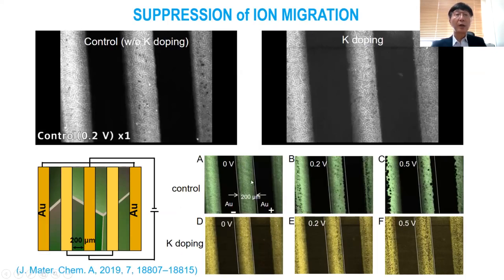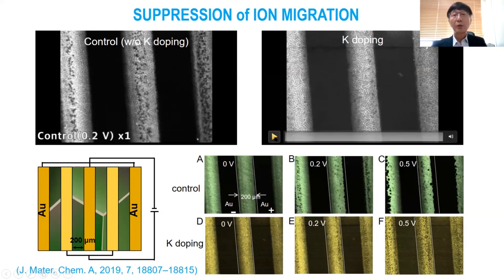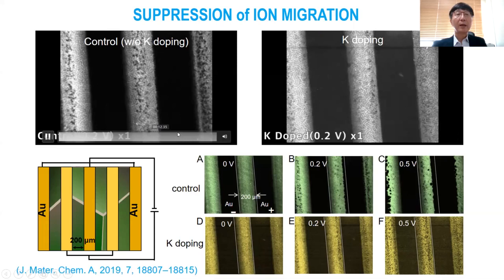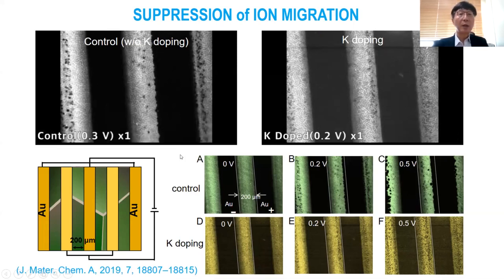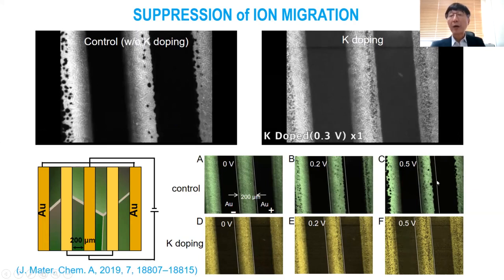So this is a visual. For instance, this is the control device, and this is the potassium-doped device. This is a PL image, an in situ PL image, and you can see that there is some disappearance of the PL image at the electrode interface. This is due to the ion migration. However, after doping with potassium, you can hardly see the ion migration.